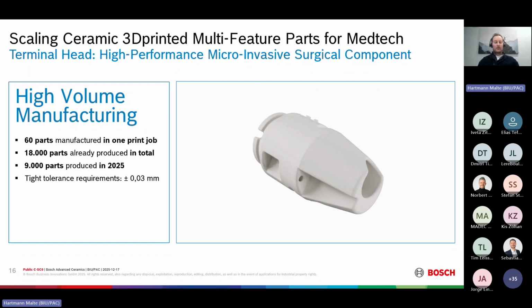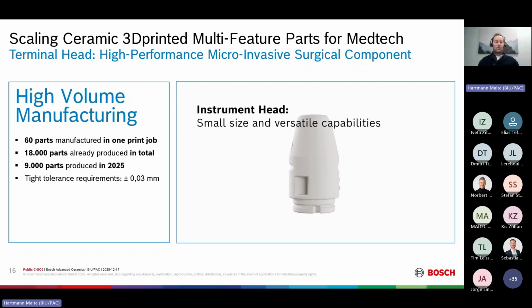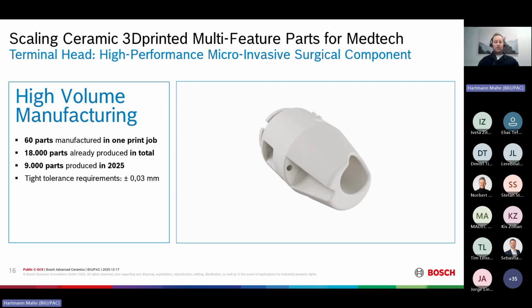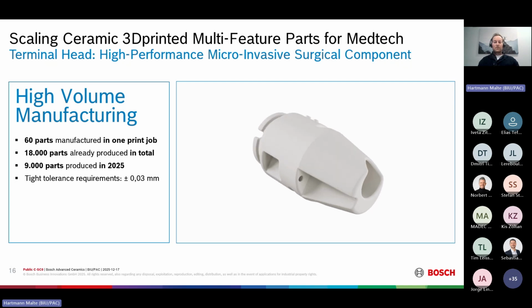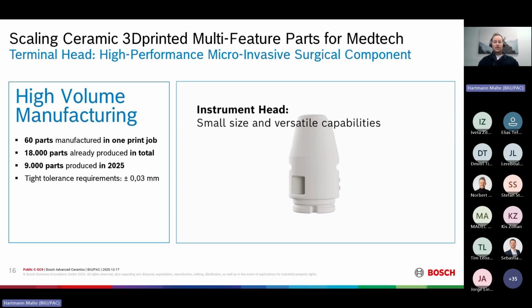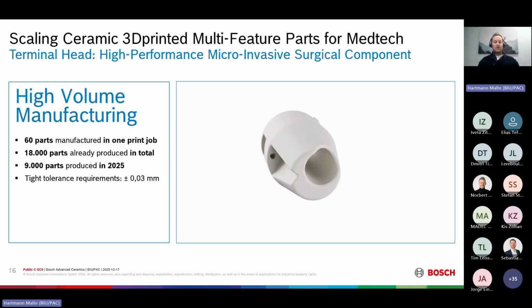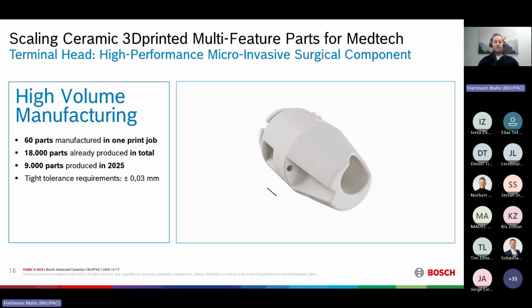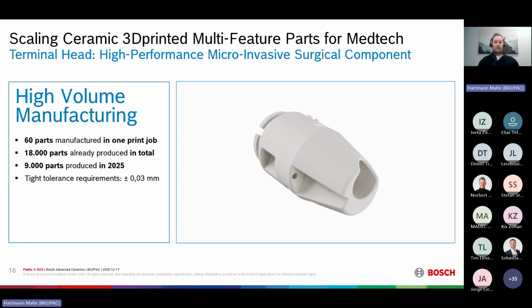There are quite strict tolerance requirements on these parts, with only plus minus 30 micrometers. And it has to be pointed out that it's not only the printing itself which is relevant to that tolerance requirement, but also other influences. For example, in those data, 11 slurry batches, 3 powder batches, 5 furnace cycles, 2 different printers, and then also the influence of different workers were influences that were to be considered.